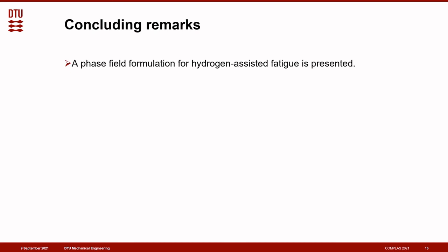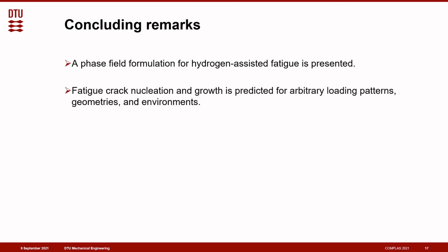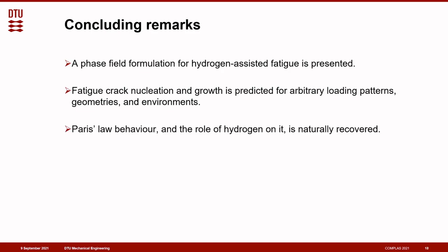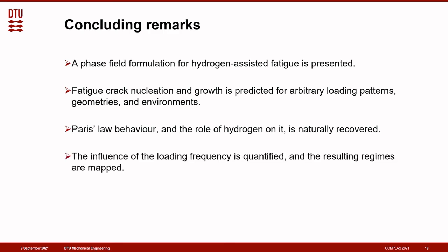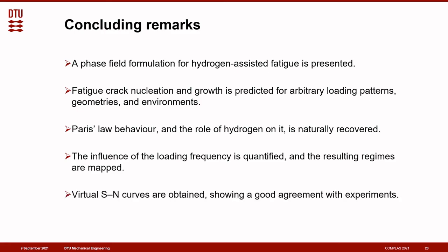Okay, and at the end, let me conclude my presentation here. We have presented a phase field formulation for hydrogen-assisted fatigue. We have shown that the model is able to predict fatigue crack nucleation and growth for arbitrary loading patterns, geometries, and environments. Paris law behavior and the role of hydrogen on it is naturally recovered by the model. And then the influence of the loading frequency is quantified, and the resulting regimes are also mapped. And finally, virtual S-N curves are obtained, showing a good agreement with experiments.